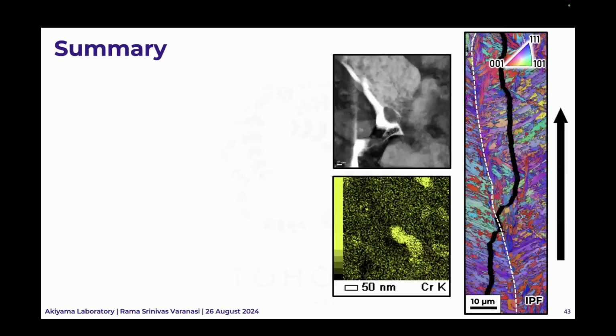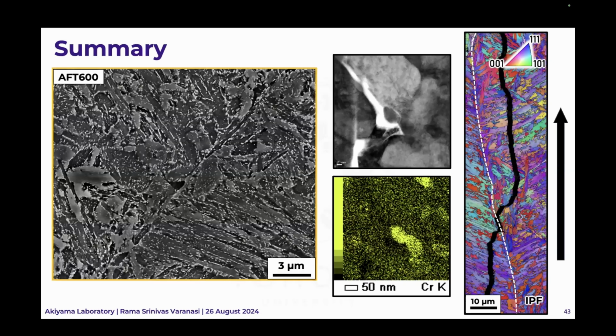Just to summarize, in Ausformed material, the prior austenite grain boundary cracking was suppressed. The smoking gun at this moment is the carbides at these boundaries, and the coverage of these carbides is much lower in the Ausformed material.